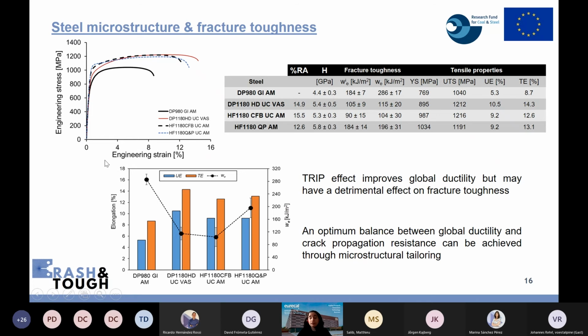Finally, if we check the properties, we can see that the TRIP effect improves global ductility. This is the main result of the project. So the TRIP effect improves global ductility, but may have a detrimental effect on fracture toughness, as we can see from the values of fracture toughness. But an optimum balance between global ductility and crack propagation resistance can be achieved through microstructural tailoring. It means that we can design the microstructure of the steel, taking into account the microstructural effects, and in this manner we can improve the fracture toughness of the material.